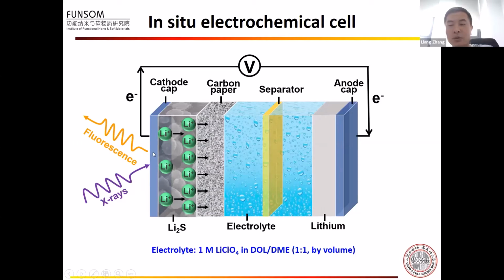Here we use a laser to drill a hole on the cathode cap, and because we cannot use the copper current collector, we use a carbon paper. We mainly measure the sulfur K-edge, and the penetration depth of the sulfur K-edge is not very high. We measure the fluorescence signal for the sulfur K-edge, and during the cycling process, we simultaneously record the XAS spectra.